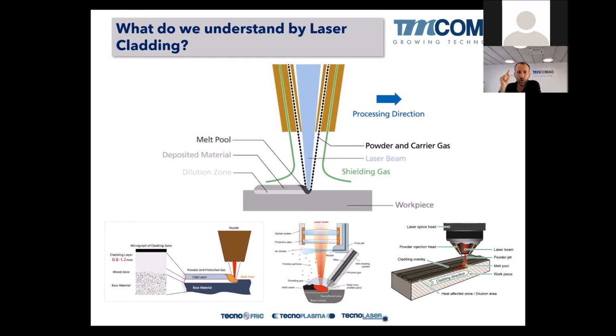Laser cladding is that welding technology with the lowest heat input to the part. That means that we will have the lowest dilution rate, the lowest mechanical warpage, the lowest mechanical distortion of the parts. And this is very important for us, okay? Because we are able to clad parts that with arc welding would be impossible, because they would distort. So it's not possible to weld these parts with conventional welding techniques.